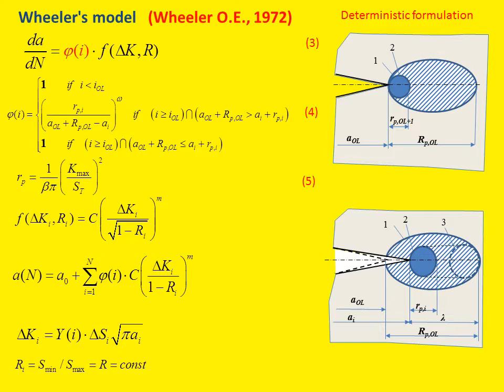According to Wheeler model, retardation will exist as long as the current plastic zone is located within the plastic zone formed due to overload. By increasing, the retardation function reaches unity, and retardation stops at the moment that the boundary of the current plastic zone reaches the boundary of the overload plastic zone. At this moment, the crack growth rate becomes equal to the crack growth rate before applying the overload. The size of the plastic zone for the plane strain case can be calculated according to equation 5.